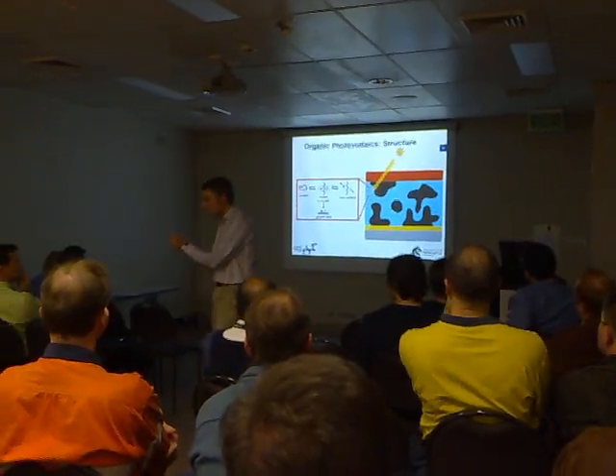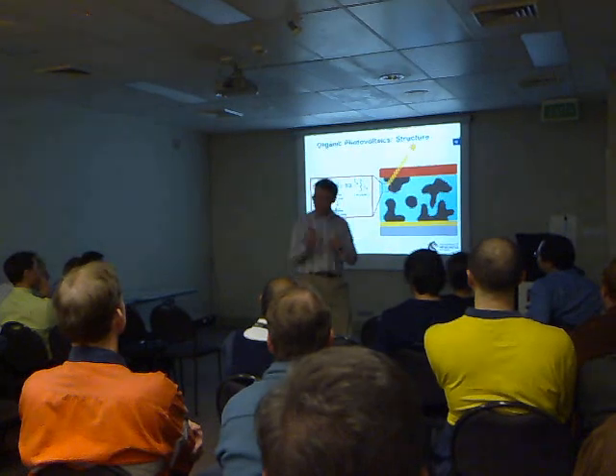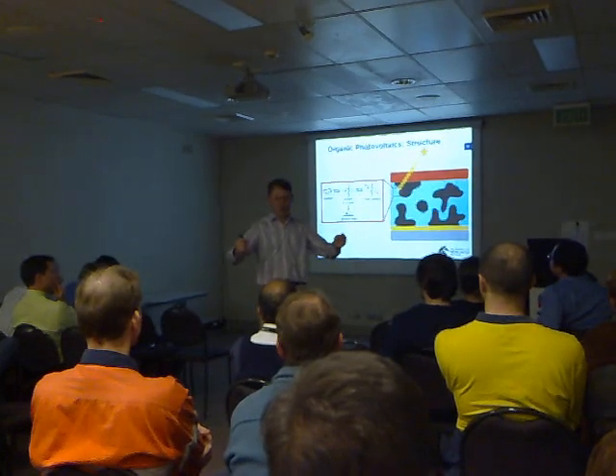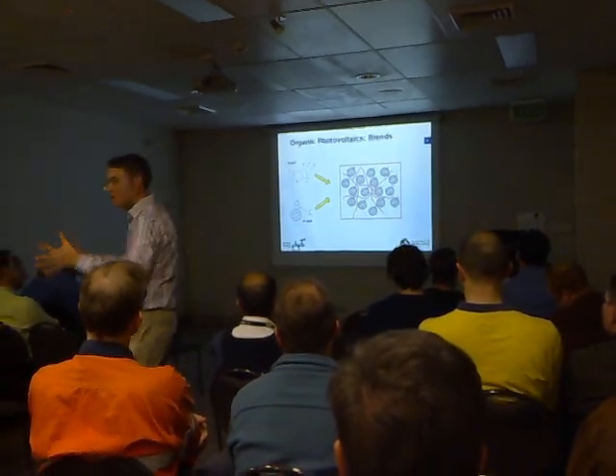So the challenge, of course, is to grab this slightly separated state before it recombines and extract the charges. How do I do that? Well, it turns out that whenever there's an interface, the electron and hole can be persuaded to hop onto different parts of that interface. They're separated by the energy level difference. Then I can create free carriers and off they go. You can see where my interfaces are — the connections between the fullerene balls and these red lines throughout this network.